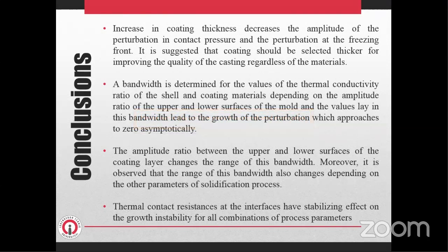The amplitude ratio between the upper and lower surfaces of the coating layer changes the range of this bandwidth. Moreover, it is observed that the range of bandwidth also changes depending on the other parameters of the solidification process. Thermal contact resistance at the interfaces has stabilizing effects on the growth instability for all combinations of process parameters.